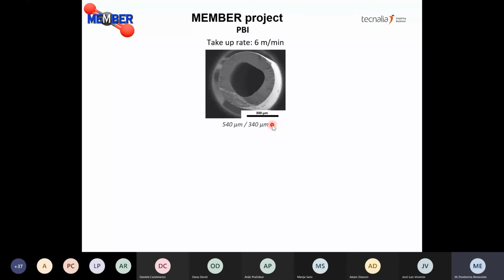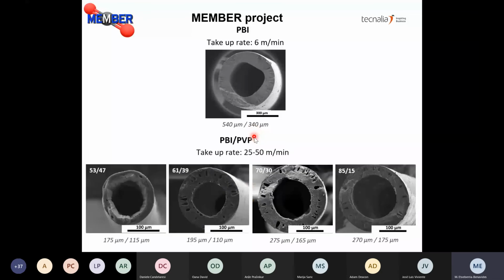So in the MEMBER project, we started producing PBI membranes. We changed the PBI supplier from the previous M4CO2 project, and also we changed the solvent used for the spinning dope preparation. We changed from dimethylacetamide to NMP. So at the beginning of the project, we tried to prepare some PBI membranes, but we were only able to increase the take-up rate up to 6 meters per minute, and this results in fibers with quite big diameter. So in order to increase the production rate of the hollow fiber, we decided to add polyvinylpyrrolidone as additive in the dope solution.